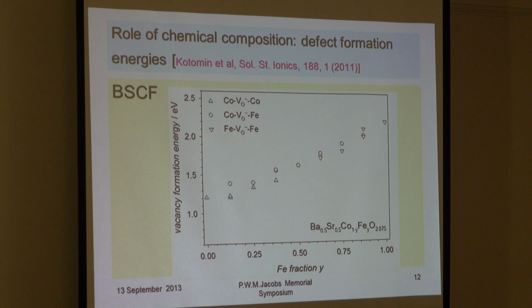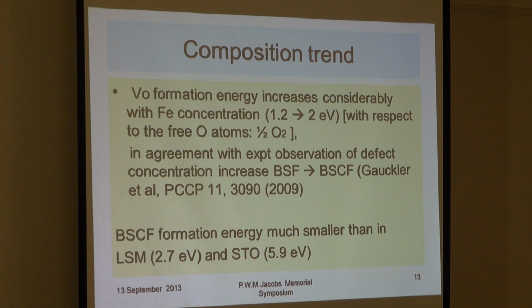What essentially you would like to have. And also when you have a mixture of say cobalt and iron, the oxygen vacancy has different local surroundings. Essentially it could be a vacancy surrounded by cobalt and iron neighbors, and so on. So we calculated also different configurations, but you can see that, okay, it's not so important essentially. At any rate, the trend is very clear. And essentially, it's in agreement with some experimental data which indicates defect concentrations in BSCF is much higher than in barium strontium ferrite, when cobalt concentration is low. So it's supported by experiment.